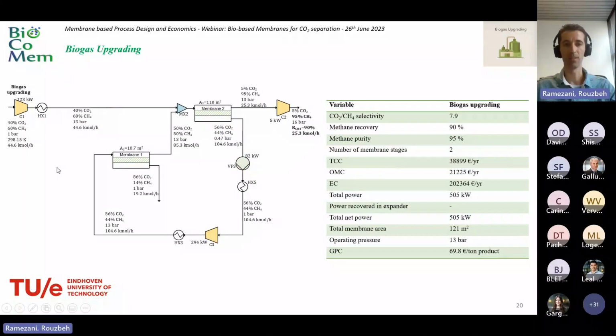So you can see in this structure for biogas, 2 stage is the best option. 2 membrane stages are enough. We can reach that target at the cost of, if I can see, 69 euro per ton product. So 2 stage for biogas is perfect. We don't need a vacuum pump for the first stage. We just need a vacuum pump for the second one. We can reach 95% methane at the second stage, at an operating pressure of 13 bar. So for this case, we need around 121 square meter membrane area.